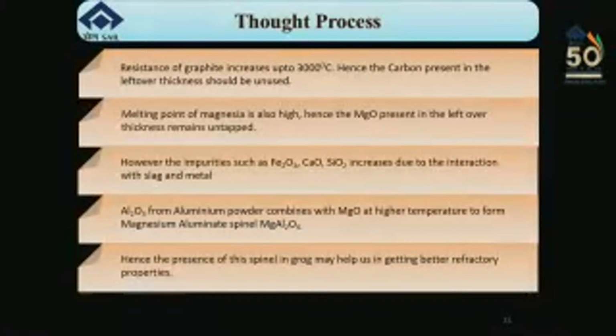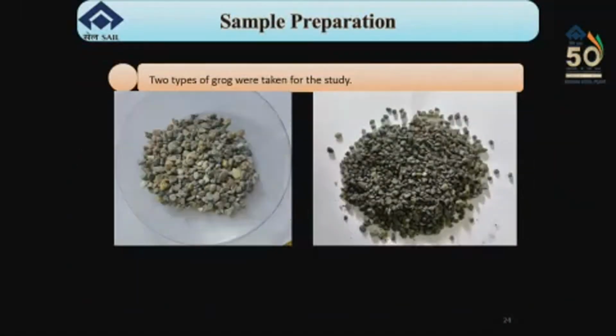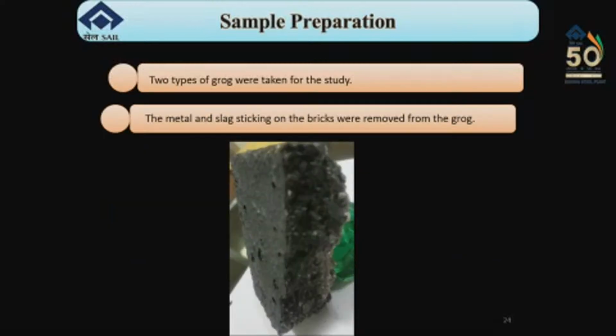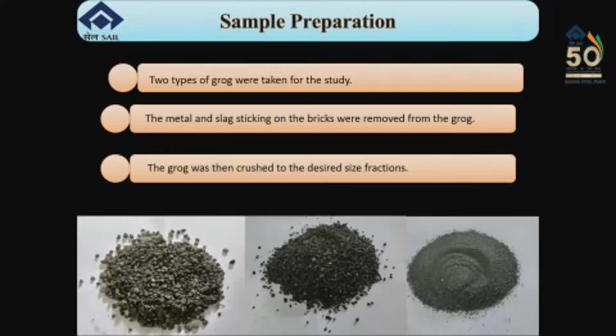So the presence of this spinel in grog may help us in getting better refractory properties. So we have gone for the sample preparation. Two types of grogs were taken for this study: one was normal grog and the other one was the calcine grog. The metal and slag sticking on the bricks were removed from the grogs. The grogs were then crushed to the desired size fractions.